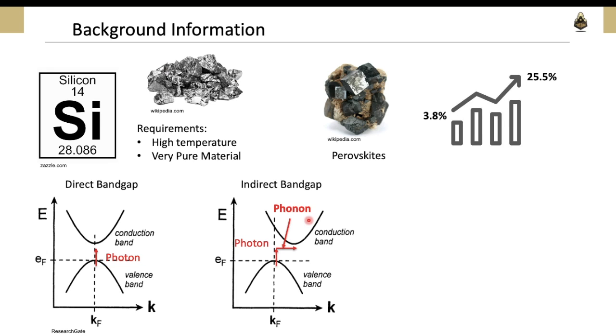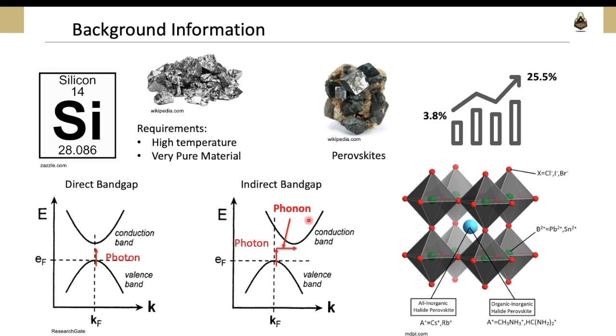Perovskites, specifically organic inorganic halide perovskites, have ABX3 structures. A is a small cation such as methylammonium, formamidinium, or cesium. B is a lead or tin cation, and X is a halide anion such as chloride, bromide, or iodide. Each B cation connects with 6 X anions to form an octahedral structure, and A fits in the free space between octahedra to form the perovskite lattice structure.